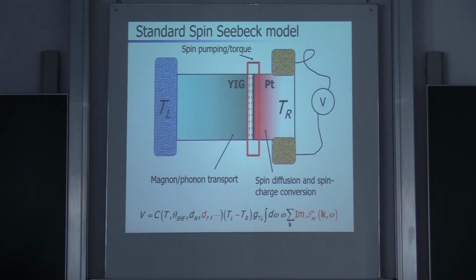Usually there are three processes involved. Directly at the interface, you have a process which is the balance between spin pumping and spin transfer torque at this interface here. So this would inject a net spin current into the normal metal. Next, there is the transformation of the spin current, which has been injected into the normal metal, into a voltage by the inverse spin Hall effect.